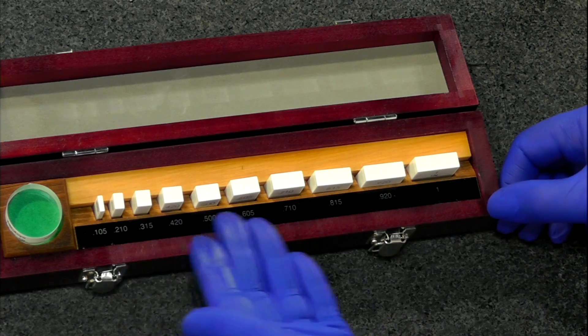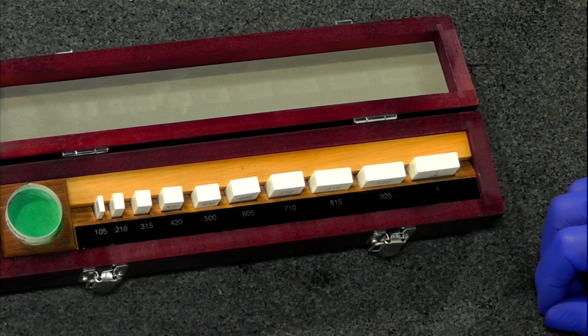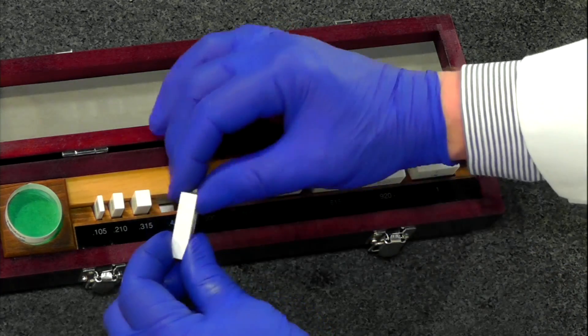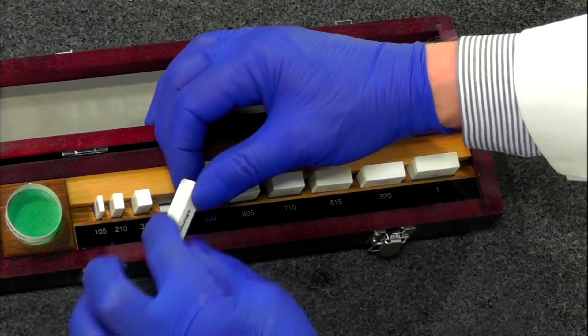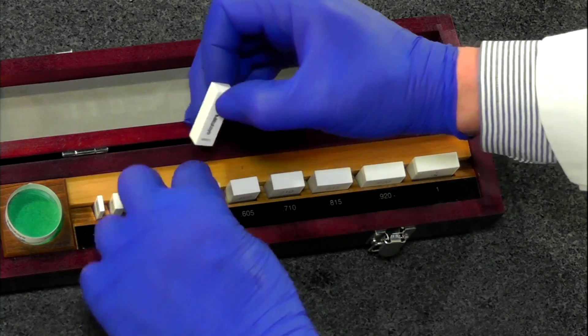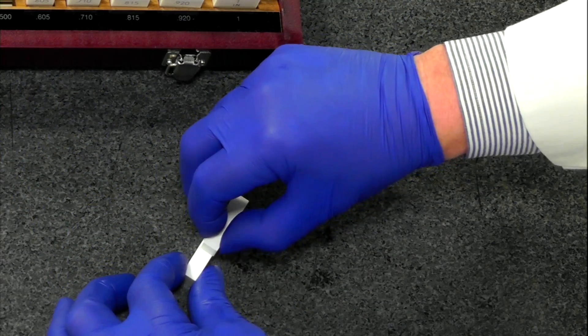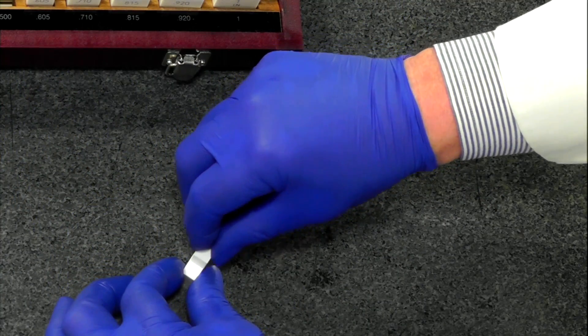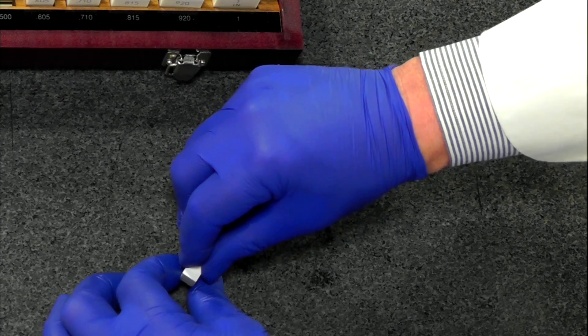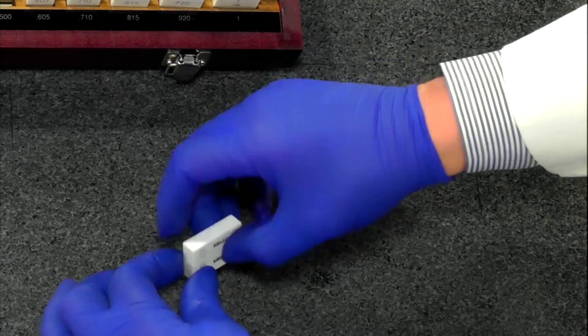They're non-magnetic, which is another advantage of ceramic. Steel gauge blocks can become magnetized and we have to demagnetize them occasionally when we calibrate — they can attract chips and metal flakes. Ceramic blocks won't attract anything. The grain structure is very tight and dense, so they tend to ring together better; they will ring a lot easier than steel ones and the contact is much tighter.